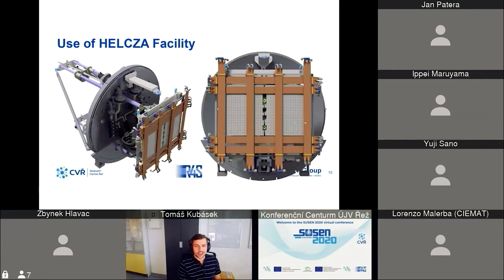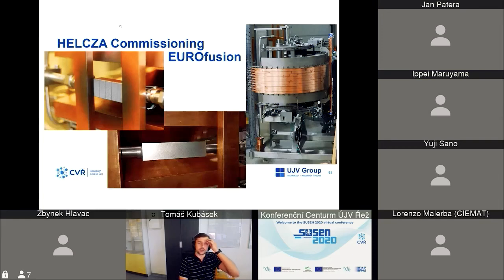Yes, so in the past few years, HELCZA has undergone a commissioning process. Firstly, for Eurofusion, like I said, we were testing divertor mockups. On the picture on the right, you can see a copper mockup of a divertor. This is not the real divertor that will be made from tungsten or wolfram, which is on the picture on the left here. Here's a small piece of tungsten from which the divertor will be made. And over here is a piece of molybdenum, which was tested in the same way as the tungsten.